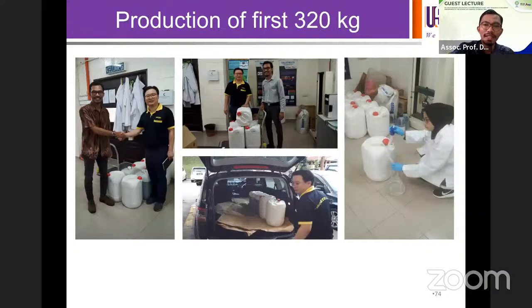So what happened is that after that, I became a businessman slightly. We were approached by a company that deals with metal industries, and they have a problem with pitting corrosion from their products, and they asked me what to do with it. So I proposed that they use a coolant in order to reduce the corrosion, and they asked me whether I have my own coolant. At that time, we were producing our own, doing some R&D, and I gave them some for free. They did their own R&D, compared with the other brands, and observed that our coolant is better than others.